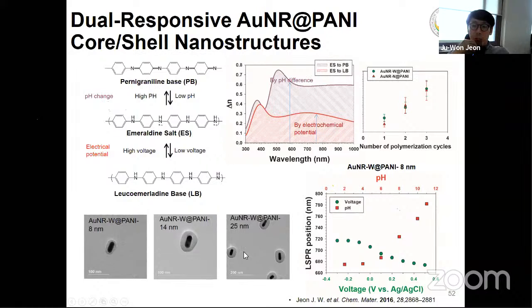So these are the TEM images of the gold nanorod and the polyaniline. And with only an 8 nanometer polyaniline shell, we can control the 100 nanometer LSPR peak position, which means with a very small amount of polyaniline, we can easily control and obtain a large modulation of the LSPR property. So this paper is separately published in Chemistry of Materials too.